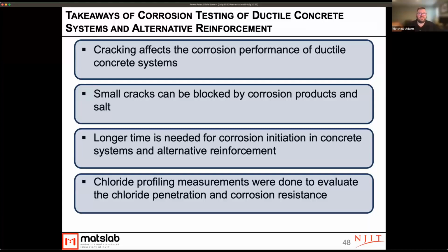And the takeaway from this is really that you don't need to go to a UHPC system for good corrosion protection for a standard system, particularly if you're not looking for those iconic bridge 150-year service lives.